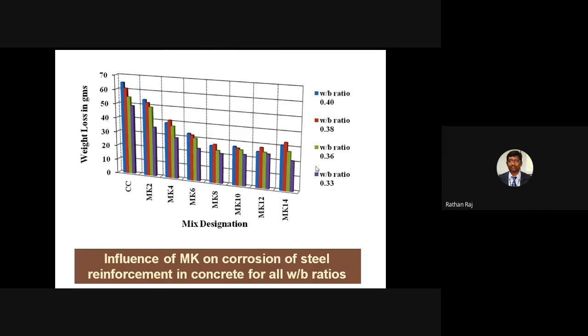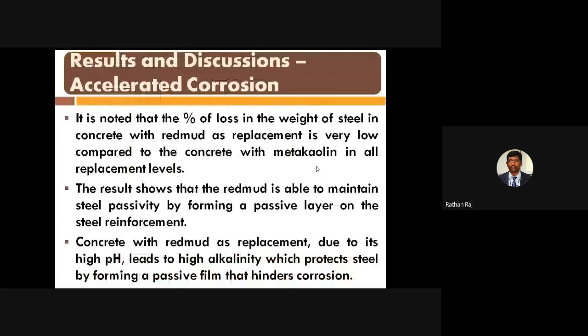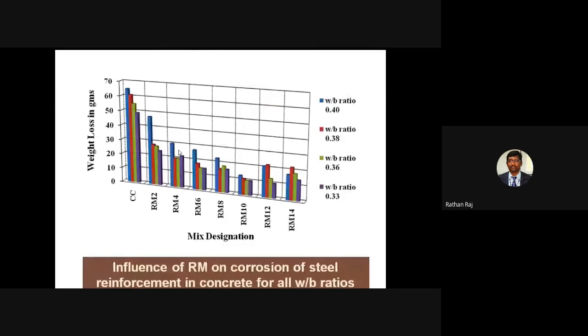So when we talk about the red mud addition, as already told, the purpose of using the red mud is that it acts as a good corrosion inhibitor, forming a passive layer on the steel because of its high alkalinity content. So due to the high alkalinity content, from the replacement starting from 2% up to 14%, there is a decrease in the loss in weight of the steel reinforcement.